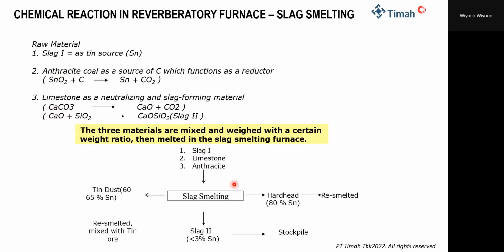We input the three materials into the furnace, slag smelting. We will get the hard head as the first product. Also, we get the second product, tin dust. The tin dust we will recover by resmelting with tin ore. Also there are the hard head and slag 2. The slag 2 has a tin content below 3%. Currently, we strive to recover tin from slag 2 in the fuming plant, but the process has not gone smoothly because of technical problems. But in Mentok we have a fuming furnace to recover the tin from slag 2.